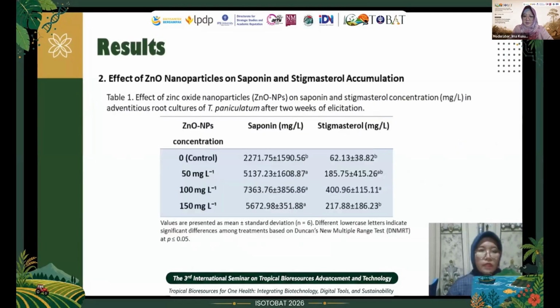Two: effect of zinc oxide nanoparticles on saponin and stigmasterol accumulation. ZnO nanoparticle elicitation significantly enhanced saponin and stigmasterol accumulation in adventitious root culture of Talinum paniculatum, like table 1. Compared with the control, all zinc oxide nanoparticle treatments increased metabolite levels, with the strongest response generally observed at 100 mg per liter.